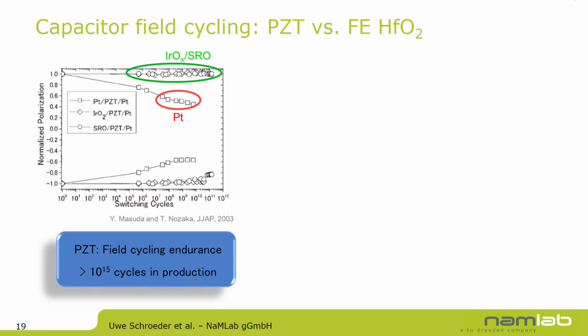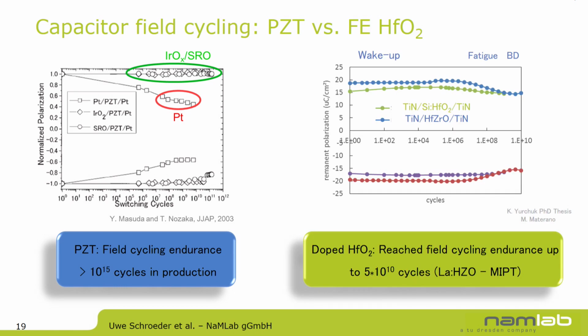Field cycling behavior in the capacitor structure. In the PZT case, it was important to have oxide-based electrodes to get really stable field cycling behavior, a constant remanent polarization value over field cycling, and not the fatigue behavior visible here for platinum electrodes. Similar for the hafnium oxide, if you optimize your material, you get quite stable field cycling behavior with almost no wake-up effect, but the polarization typically drops in the order of 10^8 to 10^9 cycles due to fatigue of the material. Currently, best values reached are in the order of 5 times 10^10. This is work from Moscow on lanthanum-doped hafnium zirconium oxide.